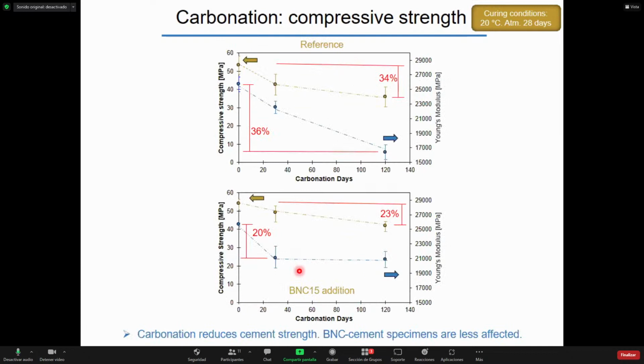Here we can see the development of strength over time after 30 and 120 days of carbonation for the reference sample and the sample with 0.15% of bacterial nanocellulose. We can conclude that in this case, carbonation reduces cement strength, but the specimens with bacterial nanocellulose are less affected.